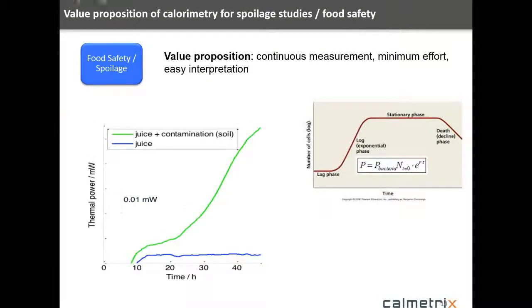So if you look at the value proposition for calorimetry in this area of spoilage and food safety, you've got the fact that it's continuous measurement, very minimum effort, easy to use, and easy to interpret the data. And what do I mean by that? Well, if you look at a typical curve here from the calorimeter, this happens to be a juice, probably like a cranberry juice, something that's very resistant to microbial activity, has a low pH, and then compared to a sample that's been contaminated. And you can see the activity, the microbial growth in the contaminated sample.